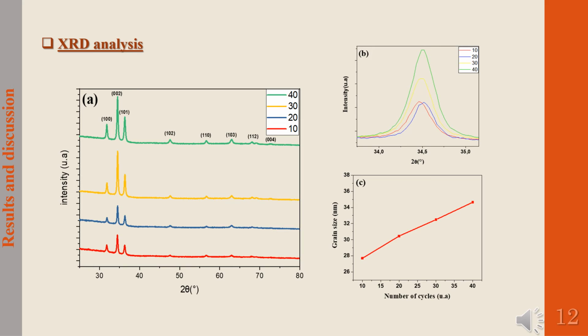The intensity of the peak 002 was found to rise in proportion to the number of cycles, as shown in this figure. This phenomenon is explained by the increase in film thickness as the number of cycles increases, with an improvement in crystallinity and film homogeneity. This was accompanied by a decrease in peak half-width, indicating an increase of the zinc oxide crystallite size from 27 to 34 nanometers, as the number of deposition cycles increased from 10 to 40.